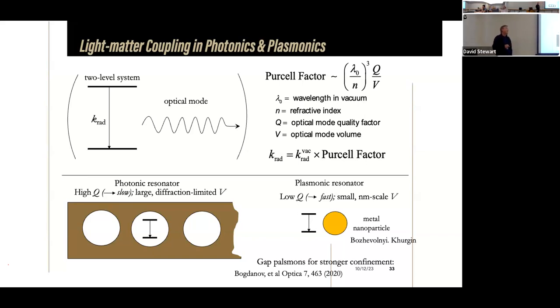And most of the groups basically try to use these dielectric cavities with very high Q, such as those based on a defect in a photonic crystal, where volume is small, but still diffraction limited, and Q could be as high as 10 to the 8. And it works. The coupling indeed increases dramatically. However, the point is you pay the price. The higher the quality factor, the slower the response of your system. So yes, coupling becomes strong, but the system responds very slowly.